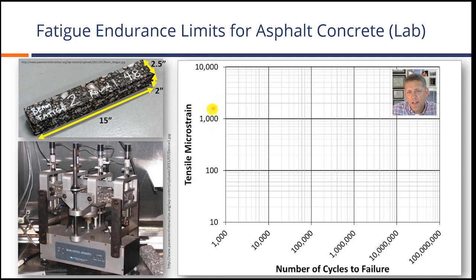And we do that at a certain strain level, and we repeat it over and over and over again and count up the number of cycles, which is on this axis, the number of cycles until the beam fails. And we normally do that over a range of strain levels. So at the higher levels, more bending, we generate relatively few number of cycles to failure, and then we drop the strain level a little bit, we get more cycles.